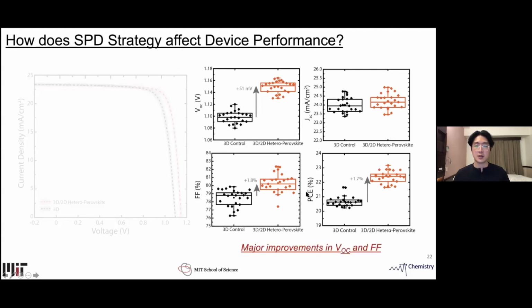We see most of the improvements from the open circuit voltage and the fill factor, which is responsible for the overall improvement in the power conversion efficiency.